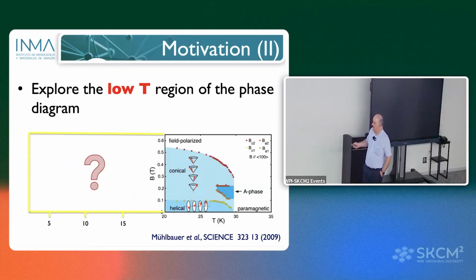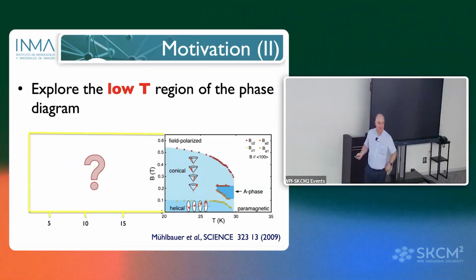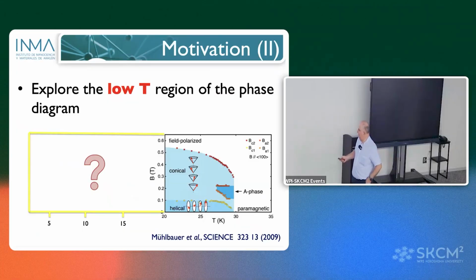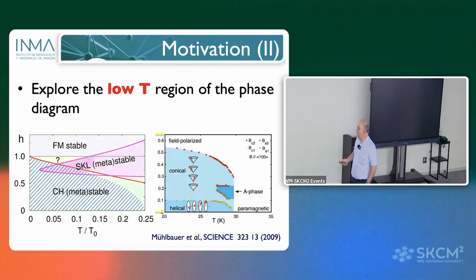The second motivation is that manganese silicide has been explored, measured and studied for, let's say, not so low temperatures. Our calculations were in this part of the phase diagram, and we found here something that we don't know. What is this? Question mark. We know that this is not a chiral helix like the one described by this simple model. They are not skyrmions, and it's not ferromagnetic. This was the second motivation.